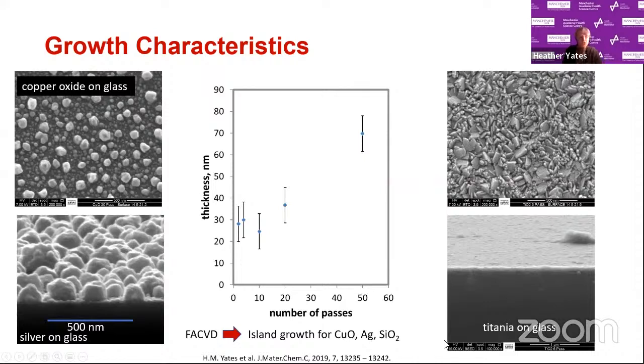So looking at growth characteristics, in flame-assisted CVD, you get what's called island growth. You can see the examples on the left, the copper oxide and the silver. It's forming small islands. So how many times you pass the coater head over that, it's increasing. But as you can see from my graph in the middle, as you increase the number of passes to start with, the thickness of the film doesn't increase. That's because you're getting a little island of the copper or the silver, and then in between it will start growing a new island. It's only when your surface gets completely covered, it then starts to increase in thickness.